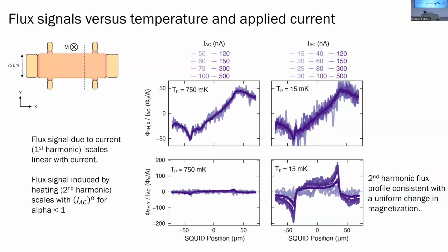It's interesting, and maybe to some this might be unsatisfying. But in transport, the two devices that we looked at look very similar. They both show quantized transport, yet the local current distribution in both devices looks very different. That is maybe concerning on the one hand, but also exciting on the other hand, because it really shows that different local current distributions can give rise to quantization. So it's a positive flip on this.